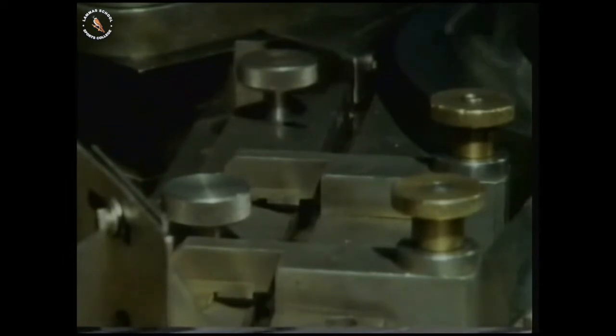This is the rimming machine. The blanks are rolled and squeezed through a channel like this, which not only impresses the letters on the edge of the blank, it also raises the rim. A blank, before it has been squeezed through the channel, is not a tight fit. But afterwards, the blank is thicker at the rim than in the middle, which explains why the finished coin is thicker than the rolled sheet we saw earlier.